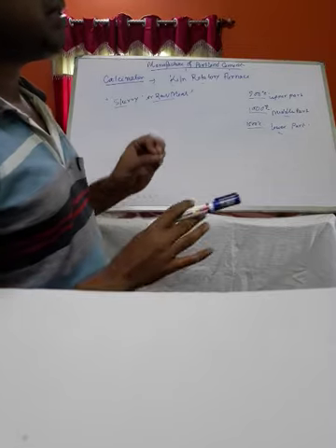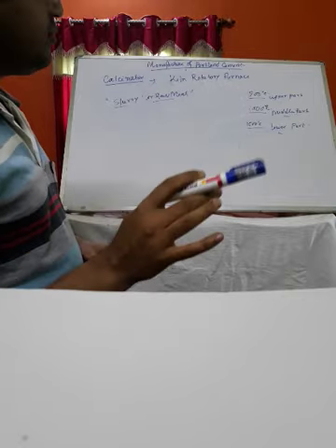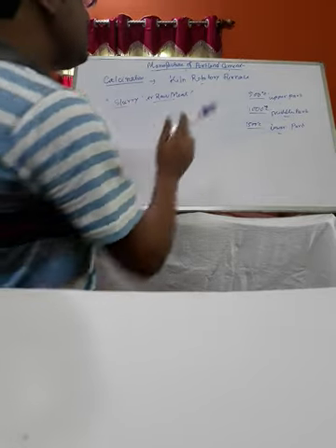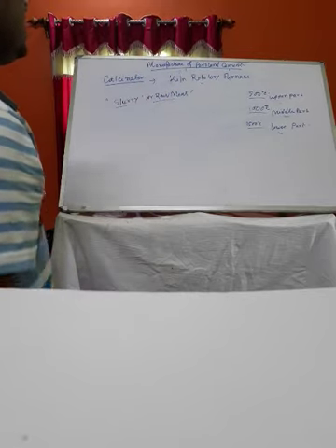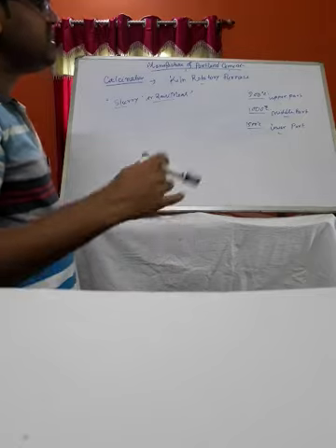Okay, now the calcination process is complete. Calcination process is done by the help of a kiln rotatory furnace. This rotatory furnace is rotated by the help of an electric motor. Now slurry or raw meal is first allowed to pass through the upper part of the furnace, and heat is applied at the lower region of the furnace. As the furnace rotates, the materials gradually descend to the lower region, where the materials are heated up to 1500 degrees centigrade. Now this is the calcination process.